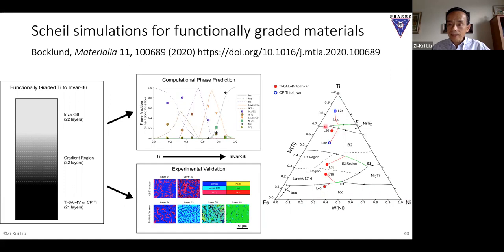On the path here, you do different shell simulations with different phases. Even in the same region, you can get the same phase. But in this region, depending on where you are, you can end up with different phases, different paths. In this region you end up there, this region you end up here, and in this region you end up there. So this can give you design guidance - some places you want to avoid, some places you want to promote.